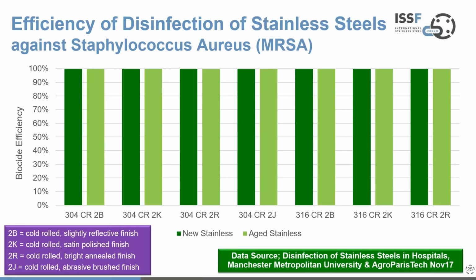Now, from a study that was carried out back in 2017, this shows the efficiency of disinfection of stainless steels against the MRSA bacteria, which we know is problematic from time to time. And what we have here in this chart is 2 different stainless grades, a 304 type, which is an 18 chromium, 8% nickel or 10% nickel steel, and a 316 grade, which is similar variant but with added molybdenum. And we have 4 different surface finishes: the cold rolled slightly reflective finish, the cold rolled satin polished finish, the cold rolled bright annealed finish, where the steel is heat treated in a oxygen free environment to retain the bright cold roll finish, so it doesn't need re-rolling to brighten up the finish, and then an abrasive brushed finish.